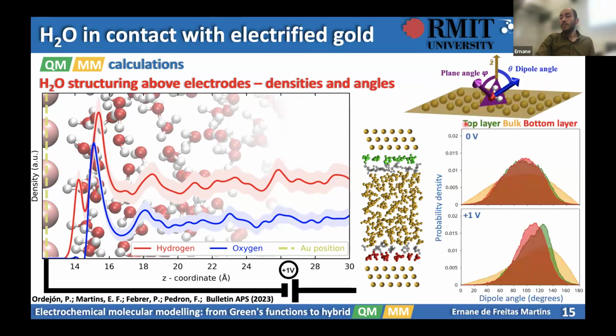If we evaluate this for the left top layer and bottom layer, in the bulk case, when we do not have a voltage, both sides are similar, and they are different from the bulk because they are interacting with the interfaces. Then when we apply a voltage, we can clearly see that they are shifted. That means the water molecules, on average, get aligned to the electric field generated here. So everything works very nicely. From this plot, you can see that it is equilibrated.